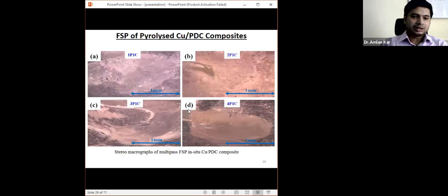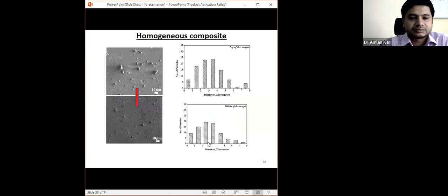And this is the macrostructure, you can see. After the first pass, this is inhomogeneously distributed, but after the fourth pass, you can see the distribution is more or less homogeneous. And you can see also there is a distribution. This is the first pass and this is the final pass. In the final pass, you can see the reinforcing particle size is substantially reduced. And the size is very, very small. Okay. And the distribution is a Gaussian sort of distribution, you can see.